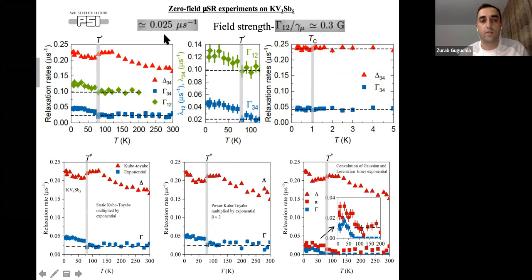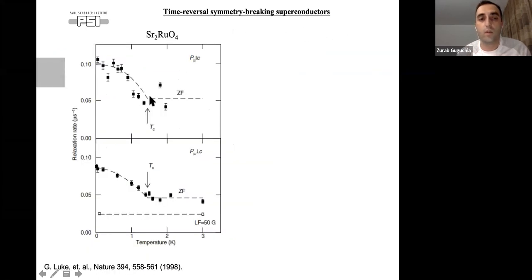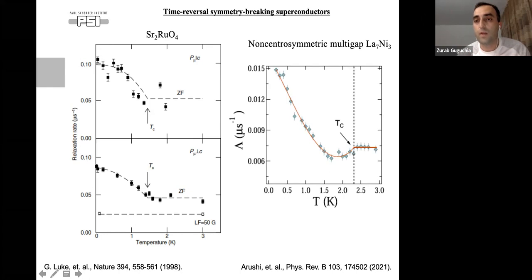The increase of the relaxation rate is about 0.025 inverse microsecond, which corresponds to an internal field strength of 0.3 Gauss. And this is more or less the value which was also found in the famous TRS breaking superconductor LaNiGa2 and a few other TRS breaking superconductors. So this is a similar field strength. I think here it is a bit higher, like 0.5 Gauss, but it is the same order of magnitude. And this kind of behavior was also observed in other multi-band non-centrosymmetric superconductors. So for the nuclear contribution we have this kind of shallow minimum.